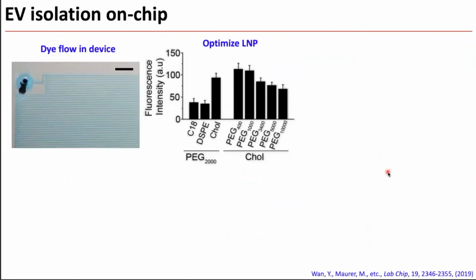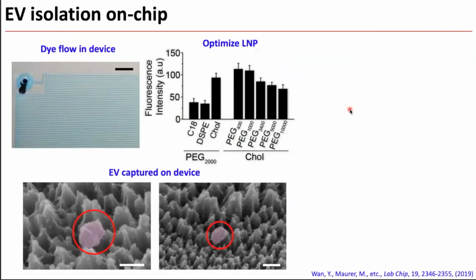So we did a little bit of further study to optimize the lipid nanoprobe. What you can see here is we used different lipid heads: monoacyl, diacyl, and cholesterol. We can see cholesterol in this particular case has a better binding capability. And then we also changed the length of the PEG linker. So the shorter the linker, the better the labeling efficiency. After we did the optimization, we can show the vesicles can be captured on the device.